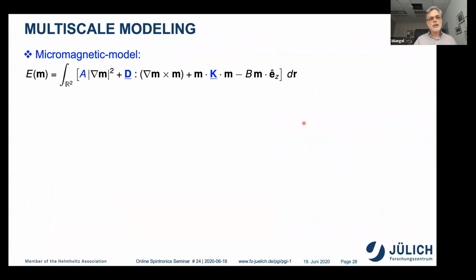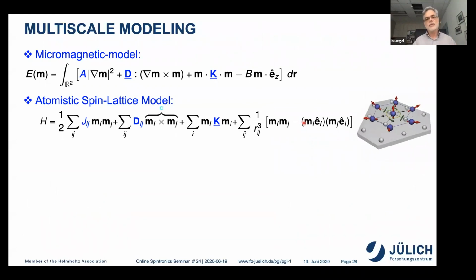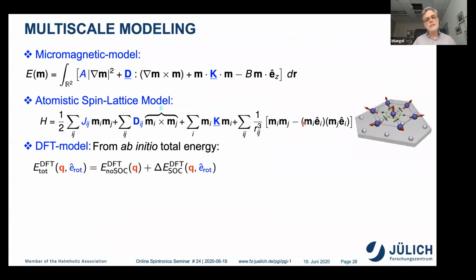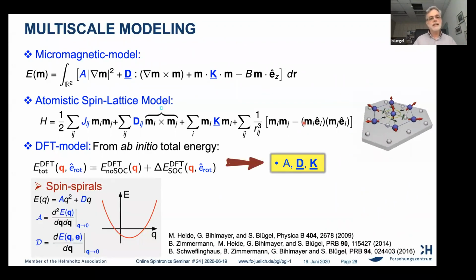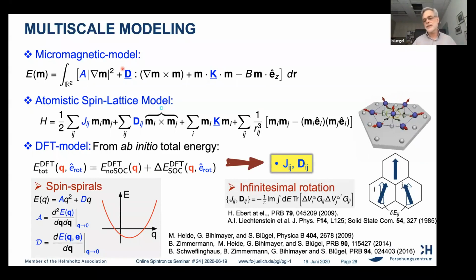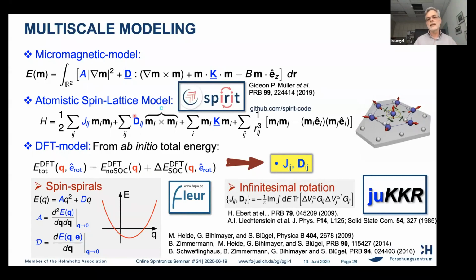Obviously, what is our approach to manage all this? On the one hand we have the micromagnetic model, in which we often think. Then we have an atomistic spin lattice model, in which we do simulation. And then we have a DFT model, from which we do ab initio calculation from the microscopic theory of the electrons, from which we then determine these parameters A and D, and of course also K, which enter into this micromagnetic model. Or by other techniques, using other methods, for example, the KKR method, calculating Dij or Jij. So basically, we have this multiscale approach, getting these parameters from the electronic structure, from the electronic properties. Think first what can happen, and then try what the simulation gives you.